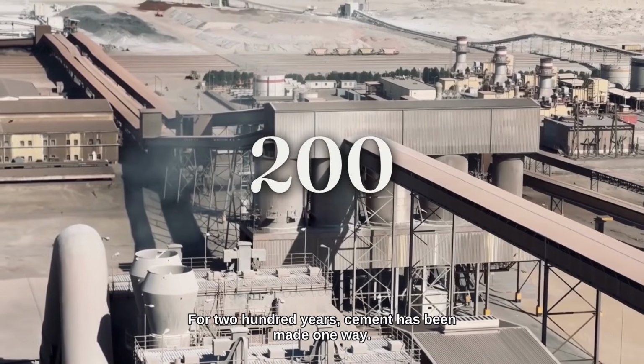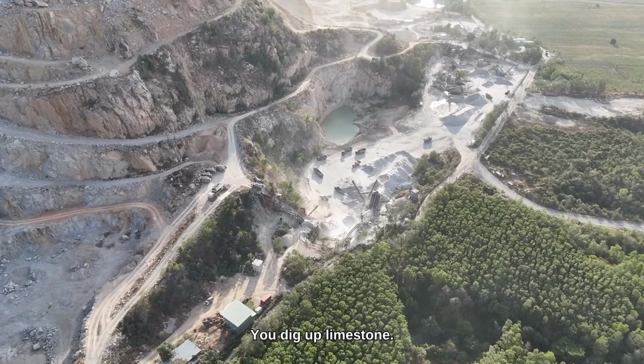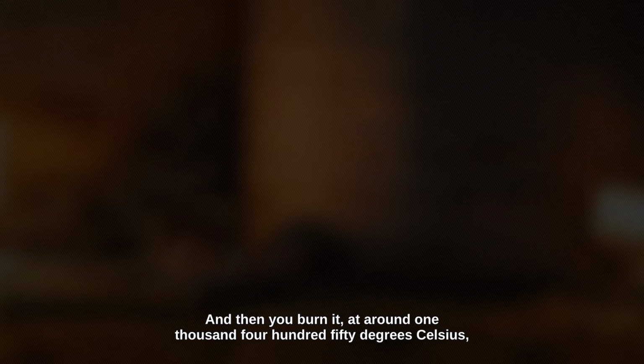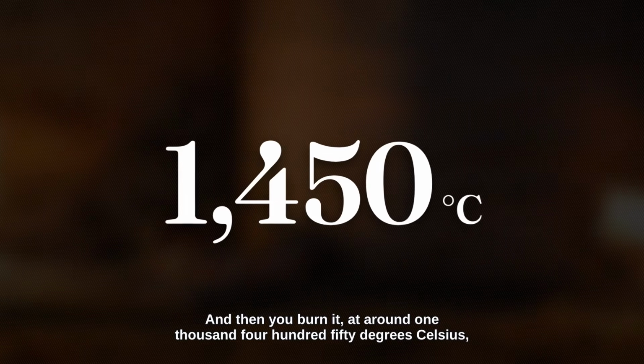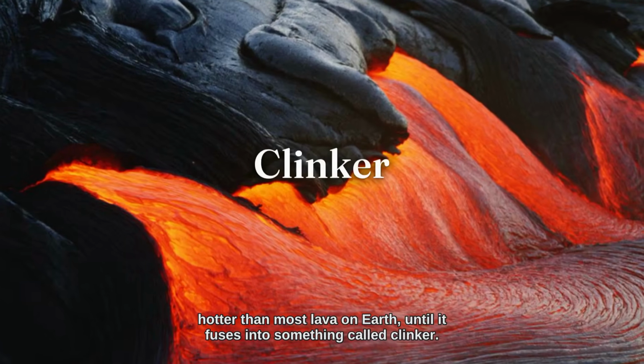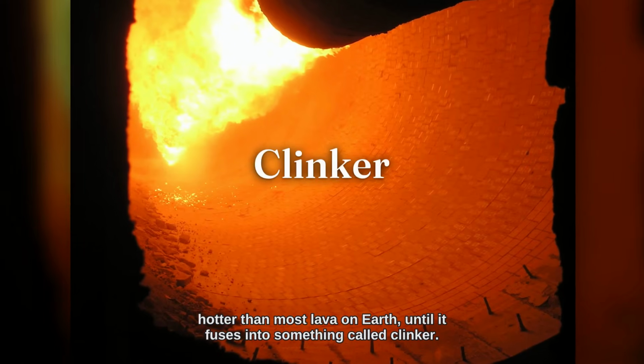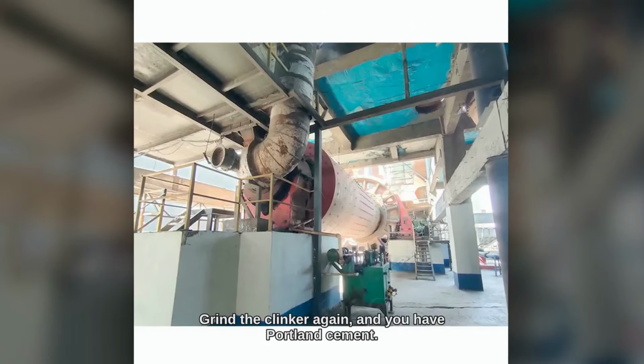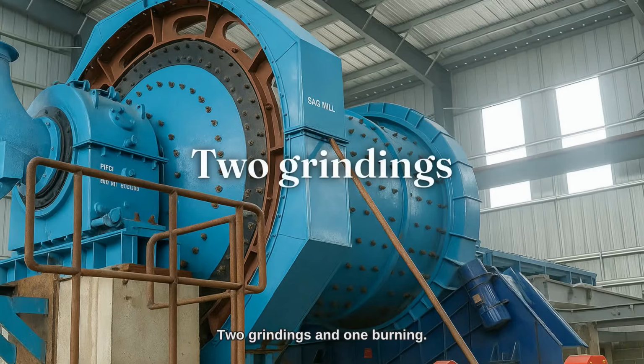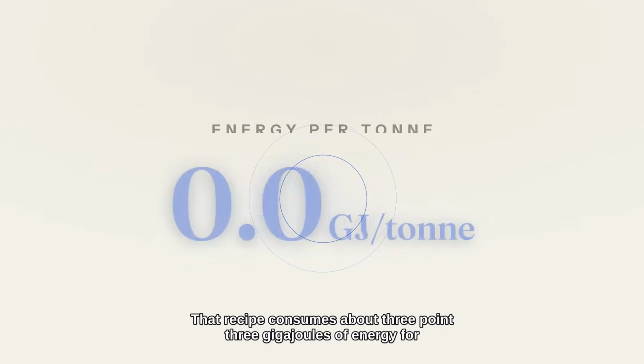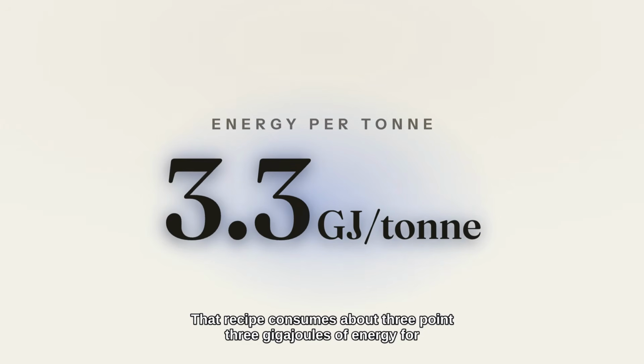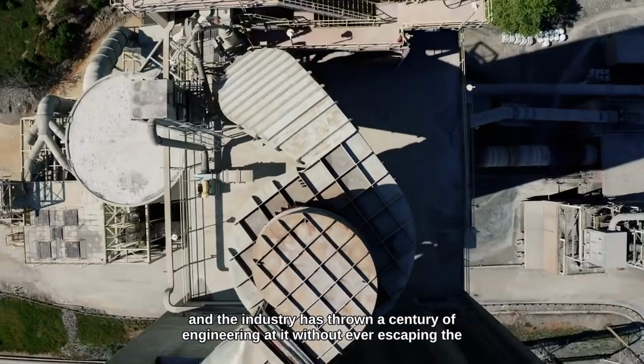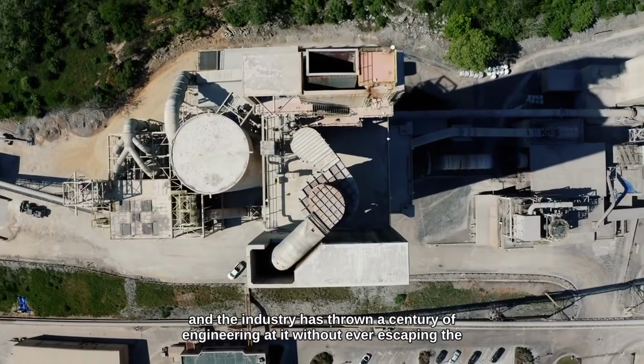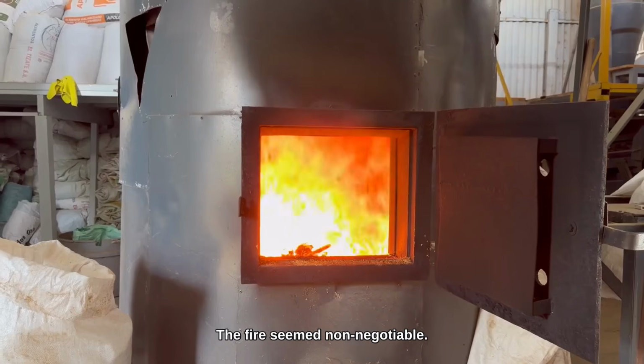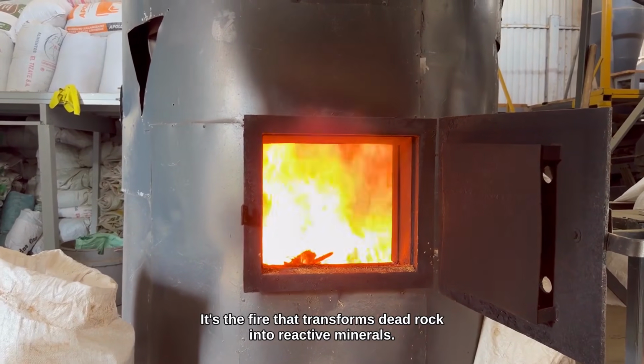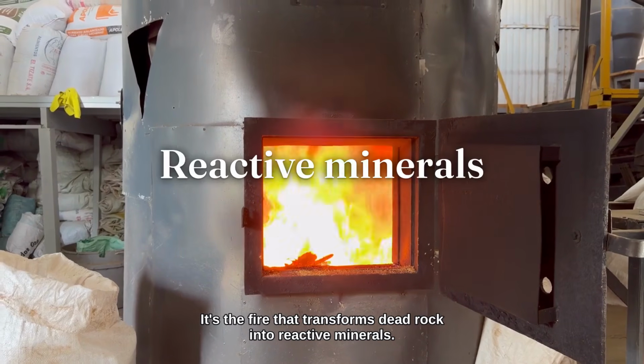For 200 years, cement has been made one way. You dig up limestone, you grind it with clay, and then you burn it at around 1,450 degrees Celsius, hotter than most lava on Earth, until it fuses into something called clinker. Grind the clinker again, and you have Portland cement. 2 grindings and 1 burning. That recipe consumes about 3.3 gigajoules of energy for every single ton, and the industry has thrown a century of engineering at it without ever escaping the fire. The fire seemed non-negotiable. It's the fire that transforms dead rock into reactive minerals.